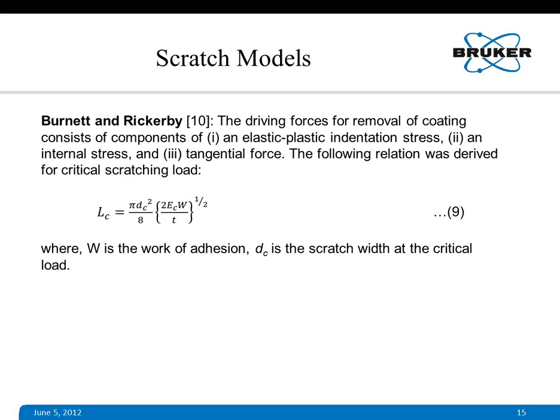Later on again, Burnett and Rickerby, they considered elastic plastic indentation stress, internal stress, and tangential force, and put forward a model for calculating the critical load LC equals pi d squared divided by 8 into 2 ECW by T to the power half, as expressed in equation 9, where W is the work of adhesion, and this is everybody's aim to find out for any coating substrate system. EC is Young's modulus of the coating, and T is thickness, of course, and DC is the scratch width at the critical load. So LC can be found out by a scratch test and all other parameters known, so W can be calculated using this model.